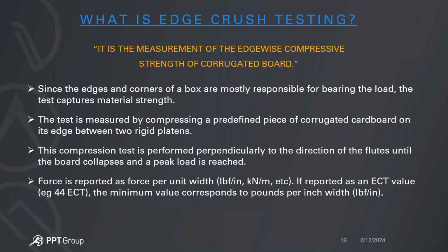This test is measured by compressing a defined piece of corrugated cardboard on its edge between two rigid platens. This compression test is performed perpendicularly to the direction of the flutes until the board collapses and a peak load is reached. Force is reported as a force per unit width, which is the width of the sample being tested. And then if reported as an ECT value, for example, 44 ECT instead of say 44 pounds or 20 pounds, the value corresponds to the pounds per inch width.